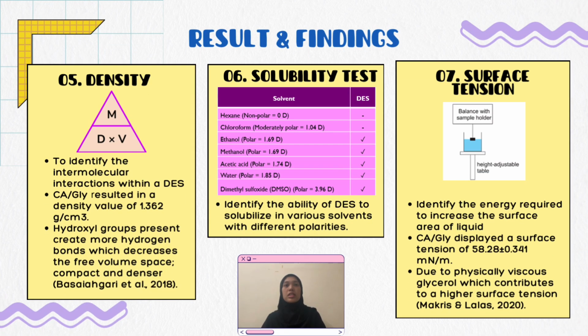The next characterization is the density test. The chosen DES had exhibited a rather dense liquid of 1.362. This is because the higher concentration of hydrogen bonds typically reduces the free volume space, which results in a more dense and compact structure overall. After that, there is the solubility test. This test is to identify the ability of DES to solubilize in various solvents with different polarities. Overall, the chosen DES was categorized to be hydrophilic, as it was miscible or soluble in highly polar solvents such as water. This is because both glycerol and citric acid monohydrate are polar in nature.